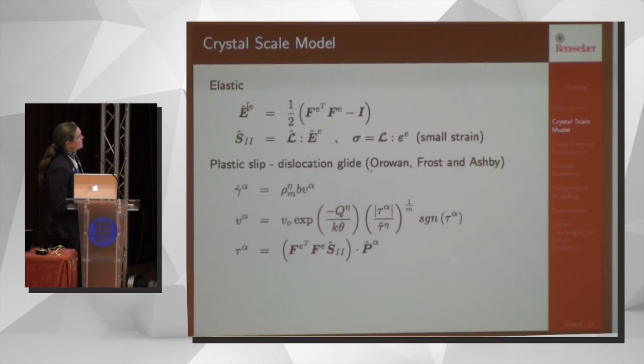And for that dislocation velocity, v alpha, I assume dislocation glide, a power law relationship, with an Arrhenius term that gives us our temperature dependence here. Theta is the temperature, Q is an activation energy for dislocation glide. And tau alpha is our driving stress, the resolved shear stress on the slip system. And tau hat eta in this case is the resistance to slip. I use eta here because eta is associated with the slip system type. So I'll talk a little bit more about that on the next slide.